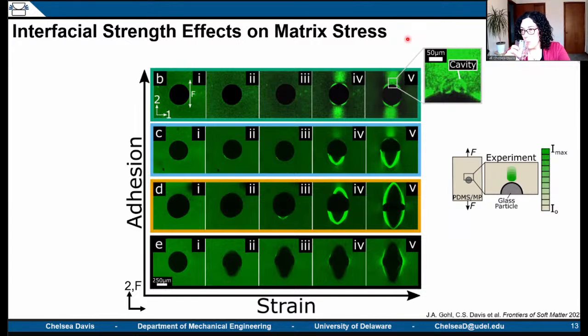All right, next question. Can you back out specific stress tensor components from the mechanophore illumination? Does the bond scission respond differently to shear versus tension, or is it some global average? Oh, I love this question. In order to perform our calibration, we needed a scalar quantity, right? We needed a value that we could plot or compare to a value. The intensity is a scalar quantity, right? Stress is a tensor, totally fair.